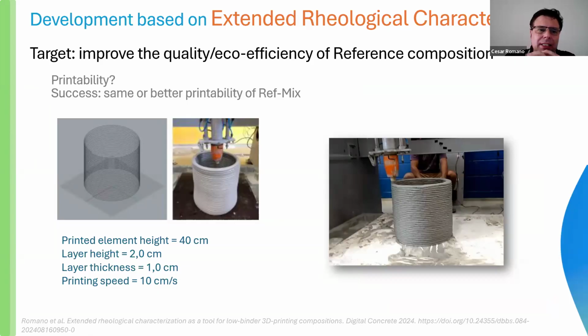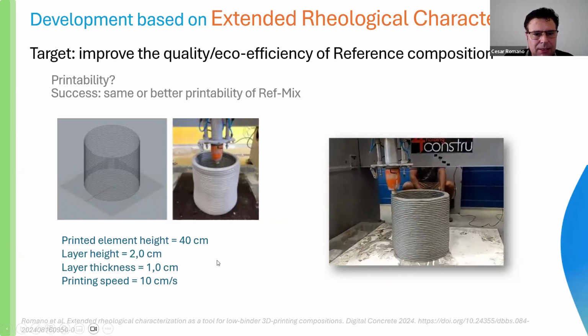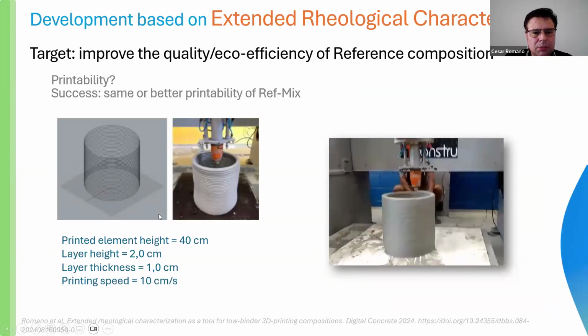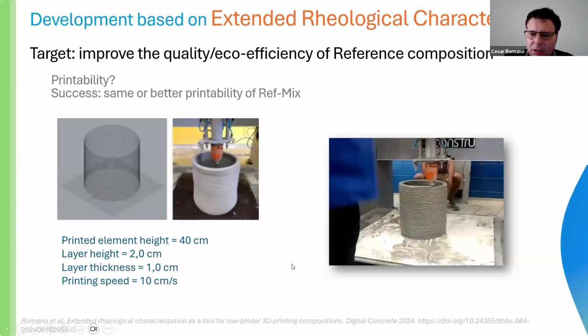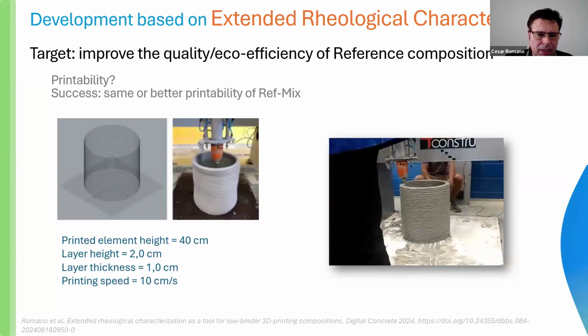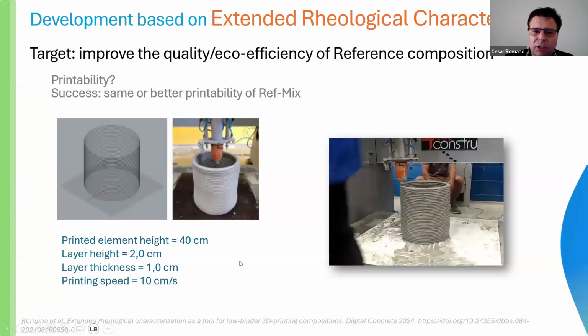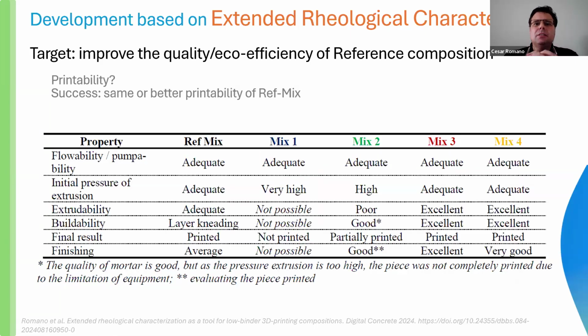So the first test we did was about printability. And the success of the test would be if we had the same quality of the reference composition. And we drew this, we produced this project here, and we started to print the materials. So, and we fixed the parameters for 3D printing. After all the printing tests, we saw that these two mixes were better than the other one, and even better than the reference mix.